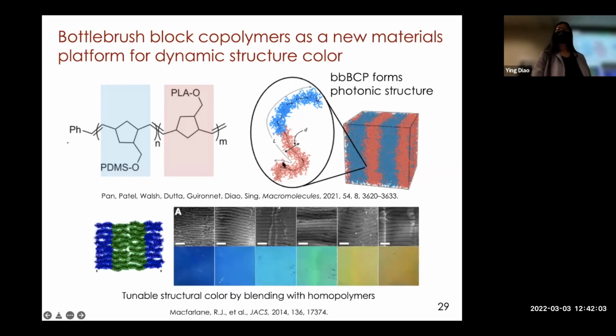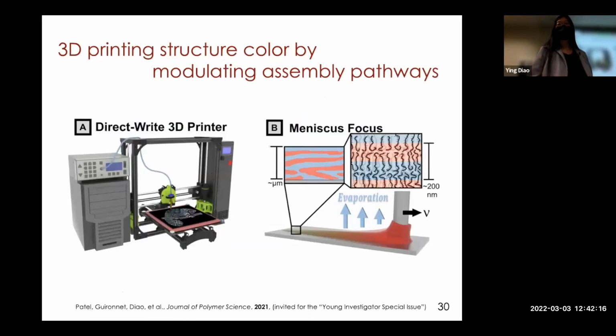So in the literature, people have tuned the assembly and the photonic properties of these materials by changing the polymers themselves or the composition. But here we're saying that we want to achieve tuning of structural color by printing. We bought these commercial 3D printers, and then we designed our own printhead and made our own software. When we print the polymer, we hypothesize that we can tune the assembly process of the polymer conformation so that we can tune the photonic properties on the fly.